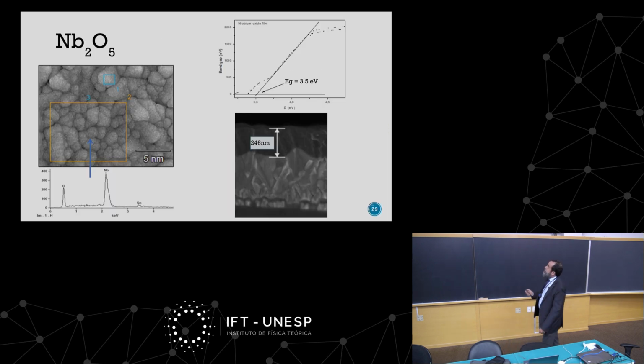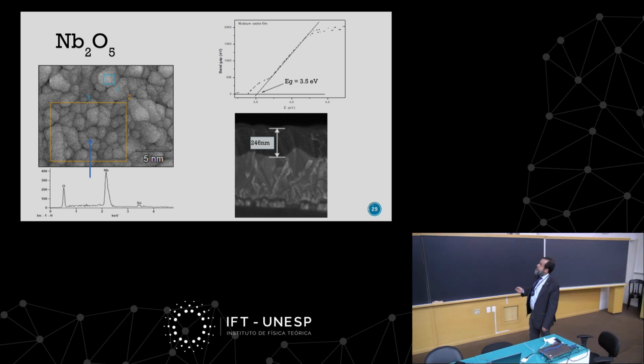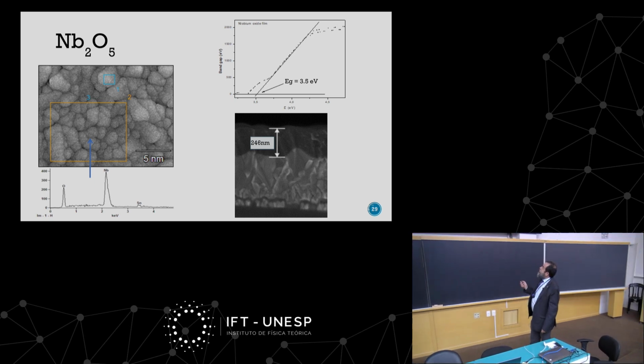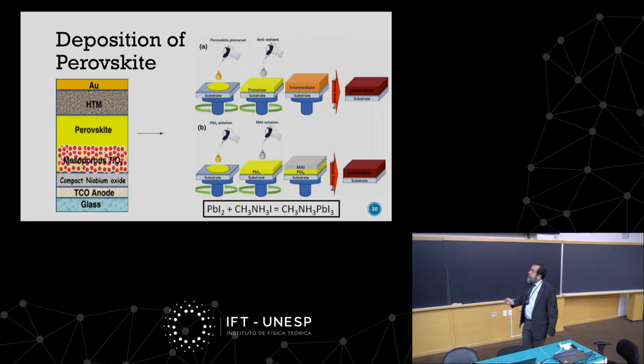And here are the films. The films are really very nice. So they are very homogeneous. We can control very well the thicknesses. We are sure that we are producing niobium pentoxide by looking at the crystal structure with the diffractometer and things like this.